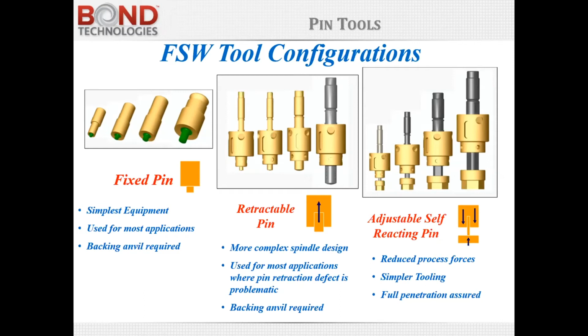One of the big benefits of this pin geometry is that the forge force is reacted not by the tooling that supports the part as much as it is by that opposing shoulder. So for launch vehicles, for example, welding a large barrel where it's very difficult or complex to introduce an internal mandrel, this has found its way into welding tanks for rocket ships.